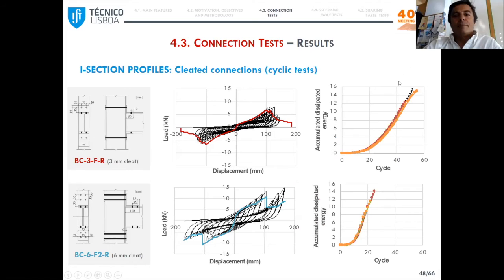Here, just as an example, you can see a summary of cyclic test results for 2 of these series with cleats with 3 and 6 millimeters of thickness. So in all series, you can see that quite marked pinching effects were observed. And comparing both, you can see that with 6 millimeters of thickness, we were able to obtain higher stiffness and strength, and also wider hysteretic curves, so associated with higher dissipated energy.